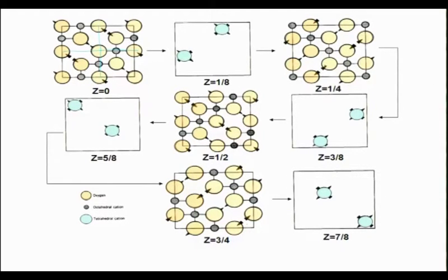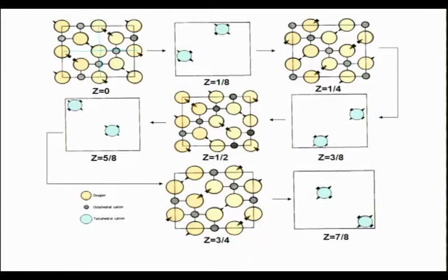So the way it fills it, it turns out 2 atoms go there, 4 atoms go there, this row remains empty, this row remains empty. Okay. The next row at Z equal to 1/8 will be tetrahedral, because now you have 2 unit cells. So that 1/4 in a normal FCC unit cell becomes 1/8, right. So 1/8 position is the tetrahedral position.